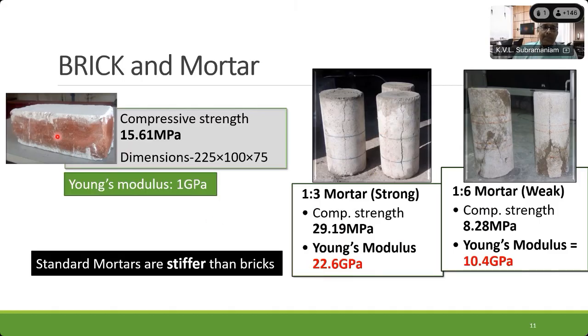But notice what happens here. This is the brick that we sourced. The compressive strength of the brick was 15.6 MPa. So that's not bad. And if you compare the compressive strength of the brick with the mortar, it lies somewhere between the weak mortar and the strong mortar. So that's actually not the problem here. Look at this, the Young's modulus. It has only 1 GPa stiffness. It's actually a very soft brick.